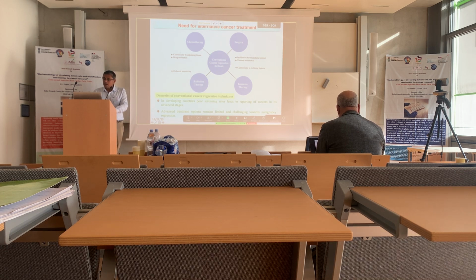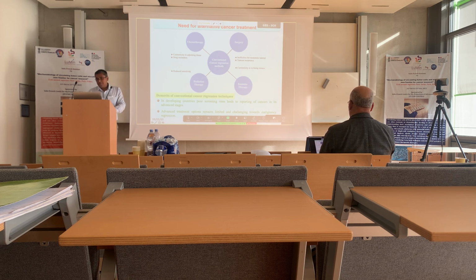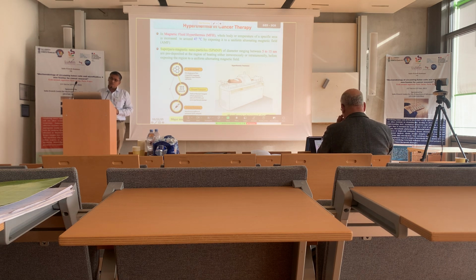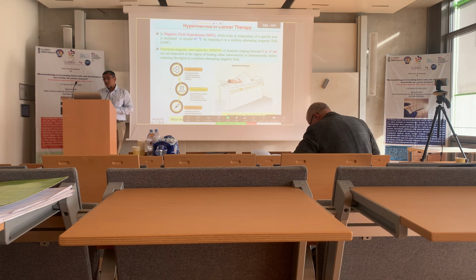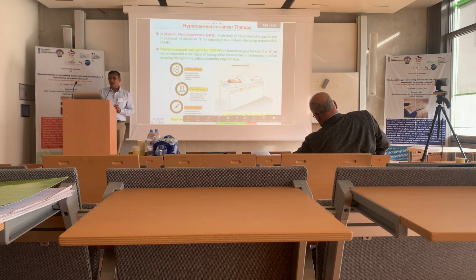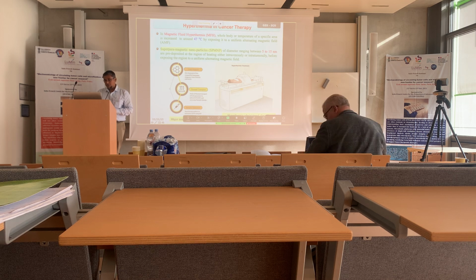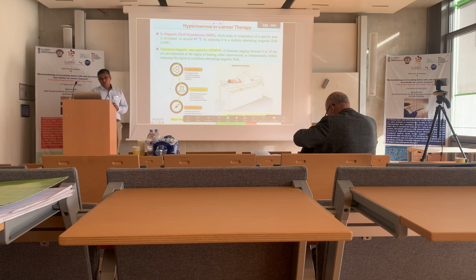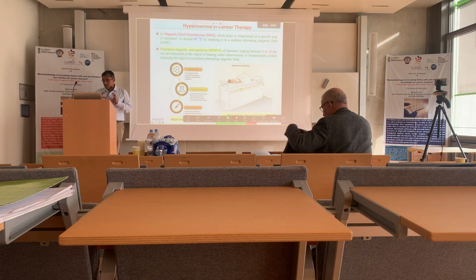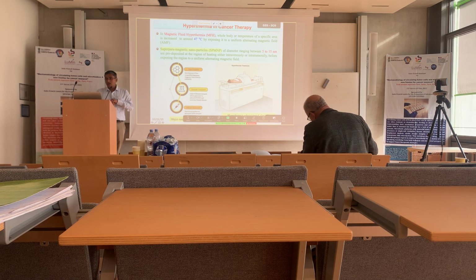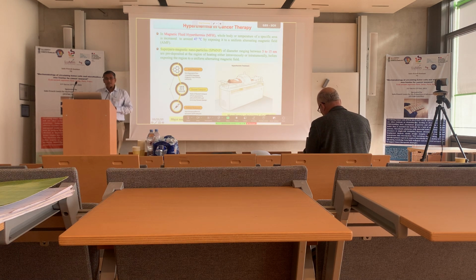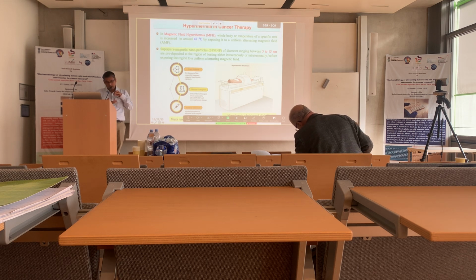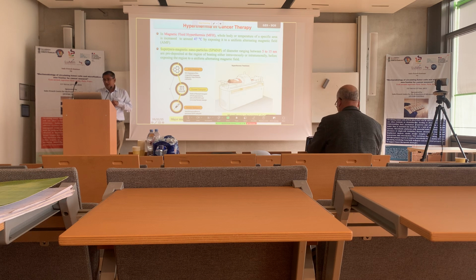Conventional cancer treatment methods are chemotherapy, surgery, radiation therapy and immunotherapy. But there are different complexities in this cancer treatment, so we have tried to find out whether there is any other alternative for cancer therapy. We have picked up magnetic fluid hyperthermia, which is basically superparamagnetic nanoparticles. If we inject them into the tumor, and this nanoparticle-enriched tumor is exposed to an alternating current magnetic field, then there is a rise in temperature. If the temperature persists at about 43 to 55 degrees centigrade, then the cell can be damaged.